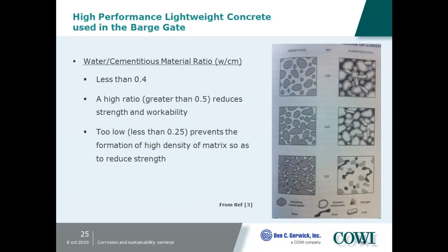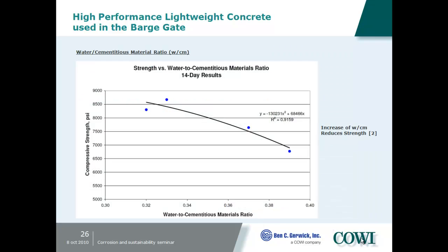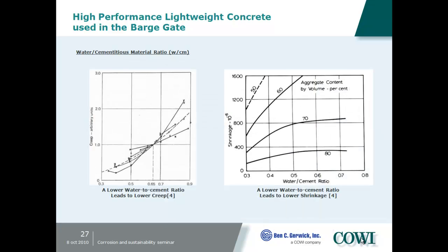Here's the good water cement ratio. We wanted to stay less than 0.4 to try to get the low permeability. I think the water cement ratio here, I probably went by it fast. It's 0.38, right, Richard? So this does show compressive strength as you get up here. We're at least over 7,000 psi with that water cement ratio, which exceeds the design criteria.